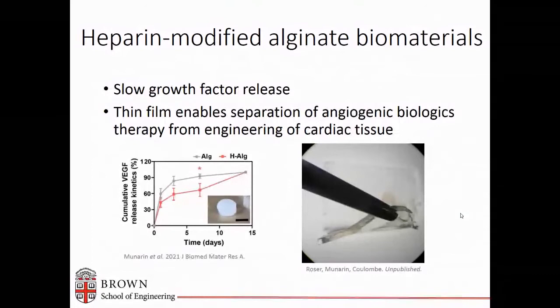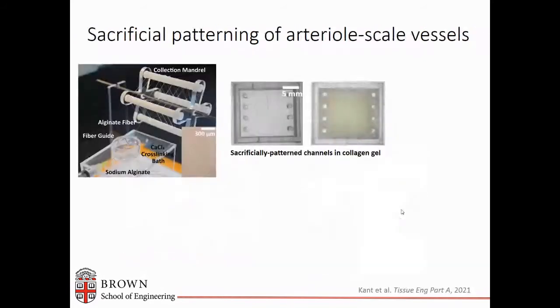So where we're moving with this project is really to use some heparin-modified alginate biomaterials to slow the growth factor release. We recently published a study to look at VEGF release using either heparin-modified or sulfate-modified alginate coming from bulk materials and microspheres. But we're also moving to a bulk sort of thin film application to be able to release the angiogenic biologics because of the need to separate the tissue engineering part with the cells and the hydrogels from the controlled release of the growth factors so that we can get the timing right on the day of repair and surgical implant.